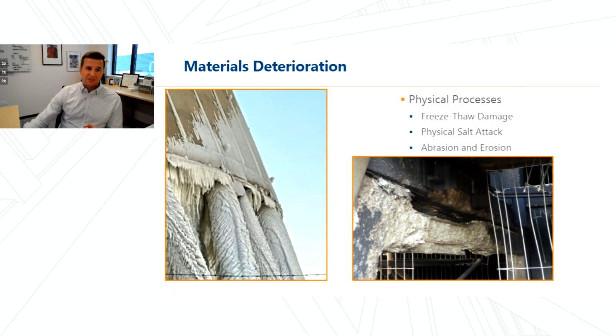In addition to chemical processes, there are also various physical processes that can cause material deterioration. The first here is freeze-thaw damage. This is simply water that expands when it freezes, and we have water within the pore structure of the concrete. When it freezes, it expands, it causes internal tensile stresses, and over time, multiple temperature cycles can degrade the concrete. It's worth noting that in power generating environments, including those in northern environments here in the US where they experience cold winters, a lot of elements don't necessarily experience the frequent temperature cycling due to the operating conditions and carrying warm water and things of that nature.